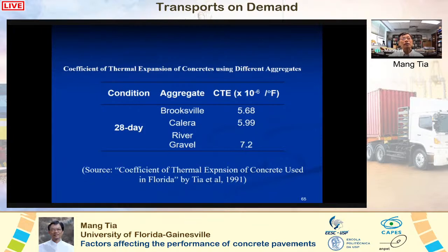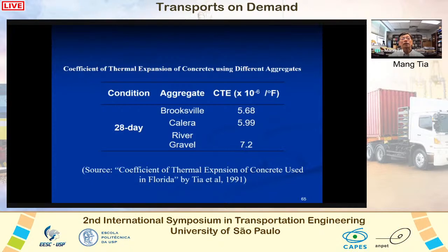Three typical concretes used in Florida, made with three different aggregates, were used in this analysis. These three aggregates were Brooksville limestone, which is a porous limestone in Florida, Calera limestone, which is a dense limestone, and river gravel. Typical properties of these concretes, as obtained from previous studies, were used as inputs for the concrete material properties. This table shows the typical coefficient of thermal expansion of concrete made with these three aggregates.